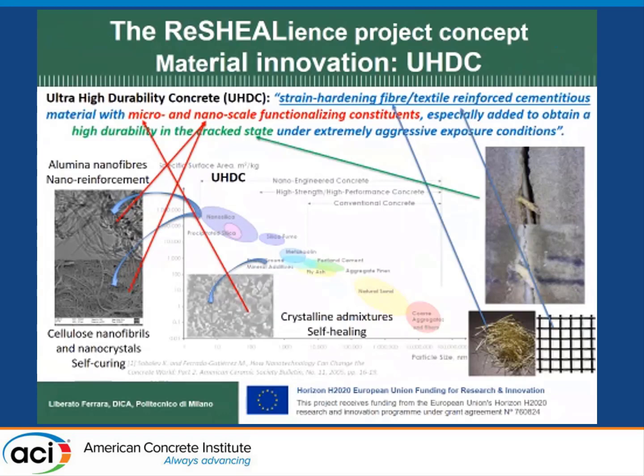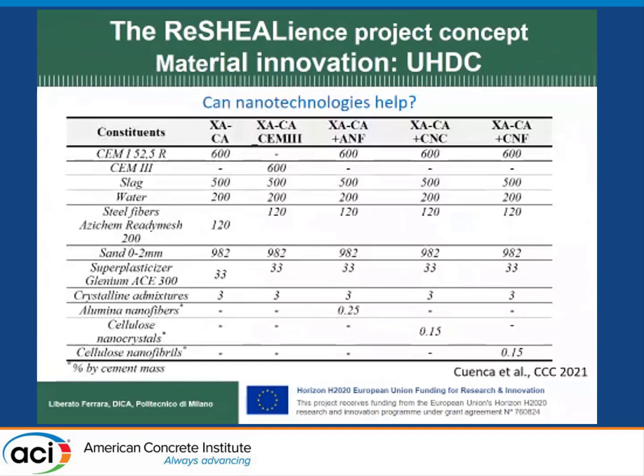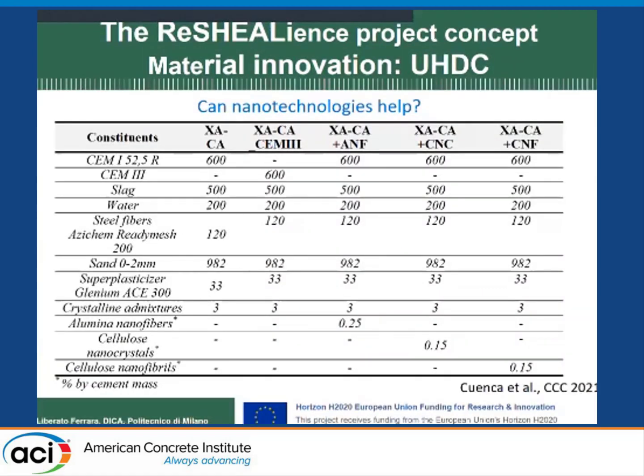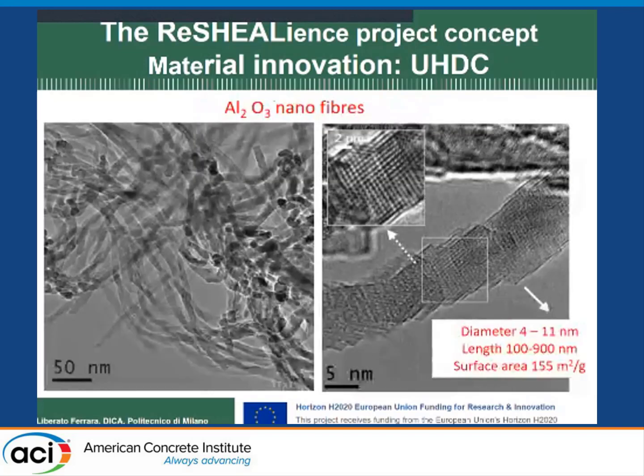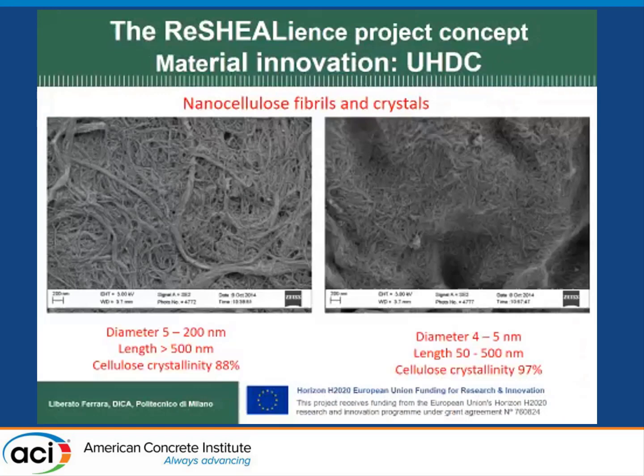And as a matter of fact, we ended up with different mixes, with a typical composition of 600 kilos per cubic meter of cement, slag in a 50% volume replacement, water binder ratio 0.18. We used 1.5% by volume steel fibers and different types of admixtures, as I said before. Some macro images of the alumina nanofibers that we have been using, or of the cellulose nanoproducts. I will be back on this a little bit later.